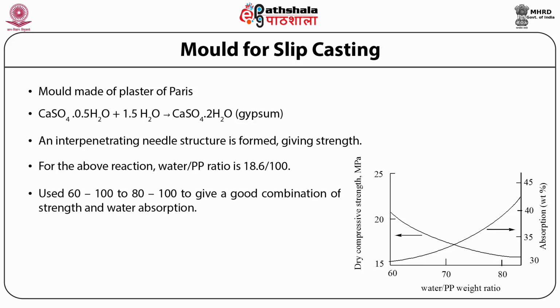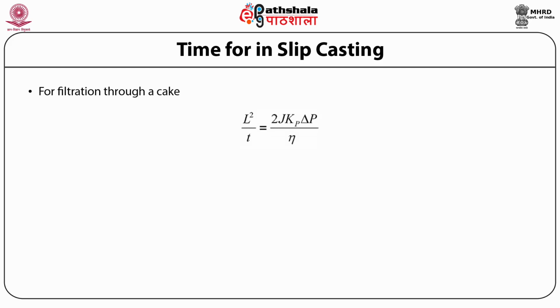So a range of 60 by 100 to 80 by 100 is used to produce the mold to give adequate porosity. The variation of the strength of the mold and its water absorption capacity with water to plaster ratio is also shown in this figure. The liquid being removed from the slurry has to pass through the cake which forms on the wall of the mold. The cake acts as a filter.